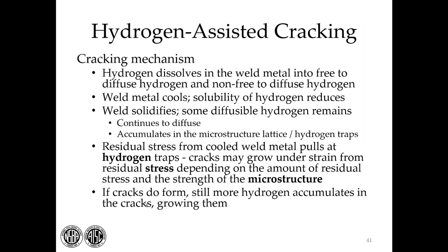When you're welding, hydrogen dissolves into the weld metal, and it comes from a variety of sources. You want to try to minimize the hydrogen for good practice, but you can't eliminate it entirely. It comes from the atmosphere, which you're keeping out with your shielding. It comes from base metal. It's within the consumable. There's always going to be a certain amount present. And when the weld metal cools, the solubility of the hydrogen reduces, and as the weld metal solidifies, some hydrogen remains. Some of it continues to diffuse out of the weld metal, but much of it accumulates in the lattice of the microstructure. So if you get enough hydrogen in your lattice, and the weld metal, and there's enough stress on your joint, and you have a microstructure that is not strong enough to resist the stress given the hydrogen traps, you'll get a crack.